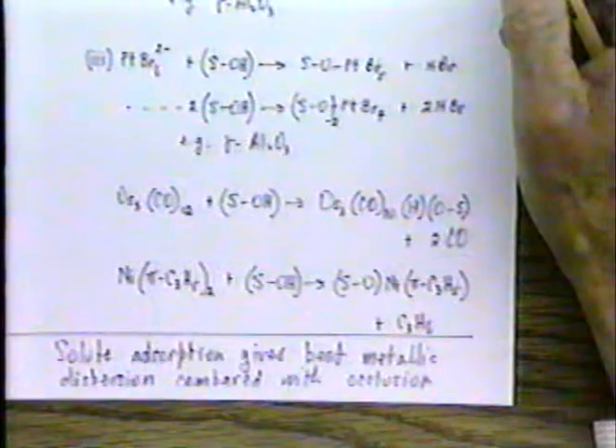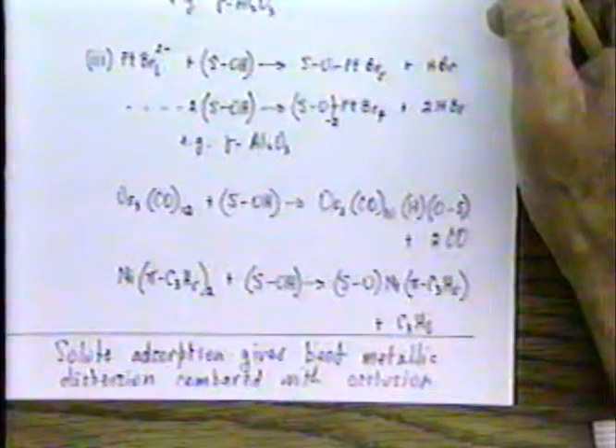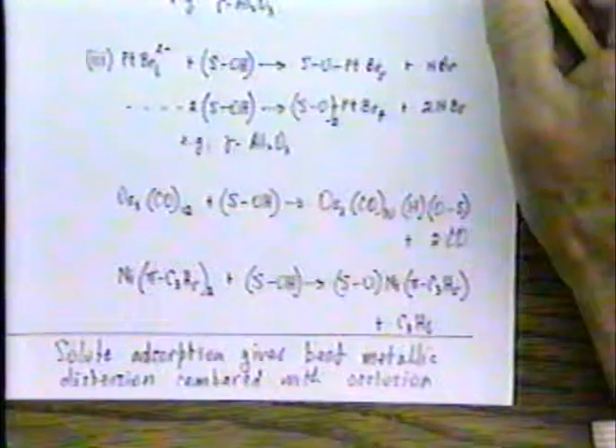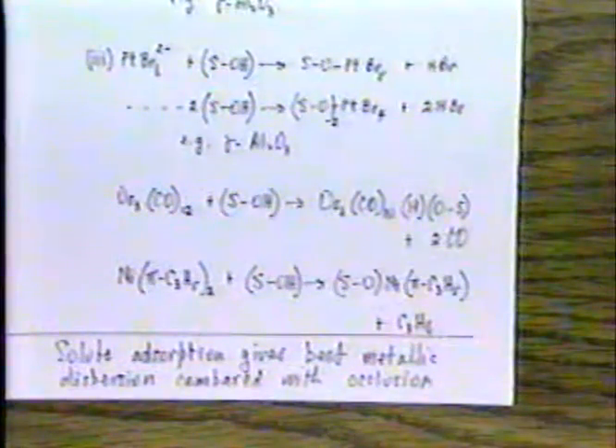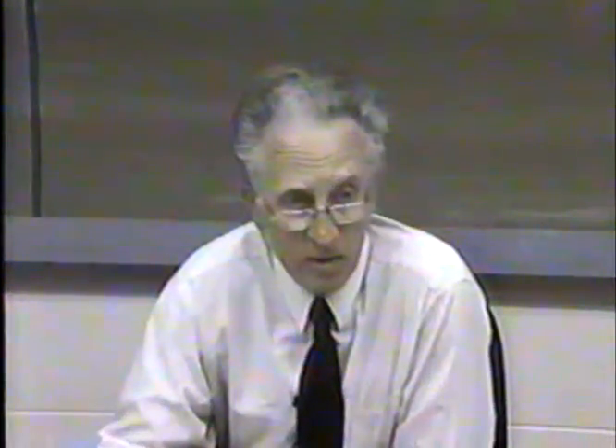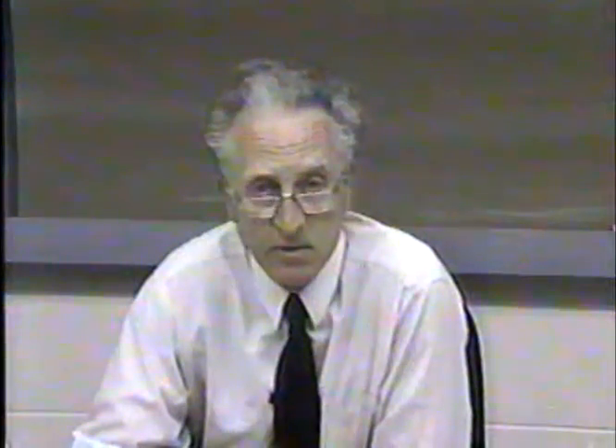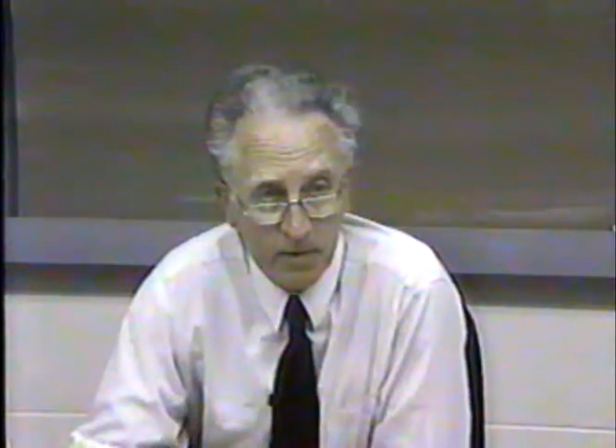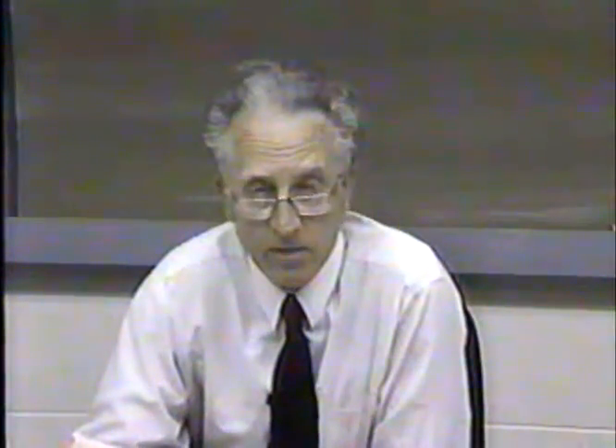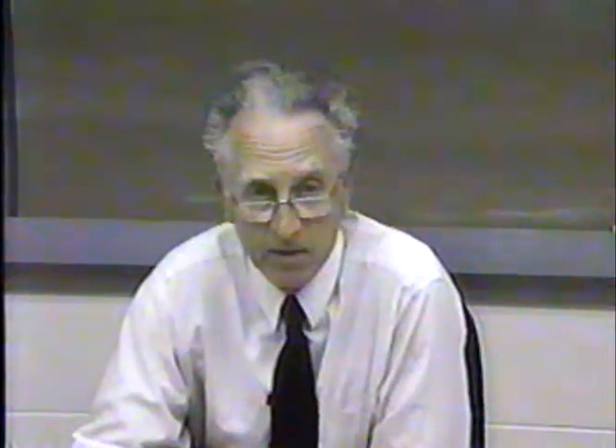And finally, before leaving this question of how you go about these preparations, let me just remind you about what might happen if you have a mixture of solutes, which may be required if you're making an alloy, if you wish to have a dispersed alloy. If you're proceeding by an occluded precursor technique, then there's little problem because the occluding solution might very well contain both solutes. For instance, precursors involving, say, platinum and gold. The occluding solution may contain both solutes which are precursors to both of these species at the start, and the result will be that when the particle is formed, it will necessarily have both platinum and gold atoms.